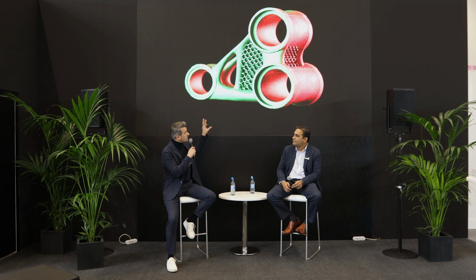What I wanted to say is, because you raised the question how we solved it: we have infill areas, we have lattice areas, we have contours, right? And we are adjusting the beam size depending on what we are doing. Also for the downskin, we are slowing down, or making the beam shape smaller, so that we get a more filigree surface. This helps us adjust in the layer itself, between lattice, contours, infill, and also downskins, and this is what helps.